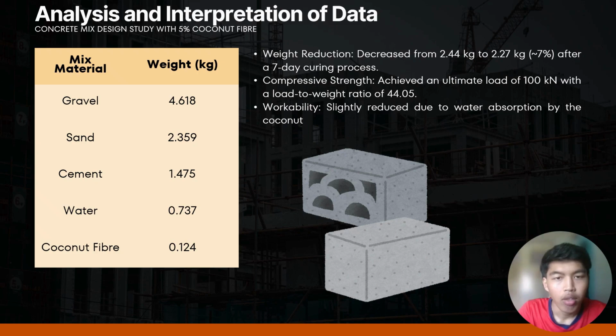After a 7-day curing period, the brick's weight decreased from 2.440 kg to 2.270 kg. This 7% reduction occurred mainly due to water evaporation and the lower density of the coconut fiber. This lighter weight offers advantages like easier handling and lower dead load.